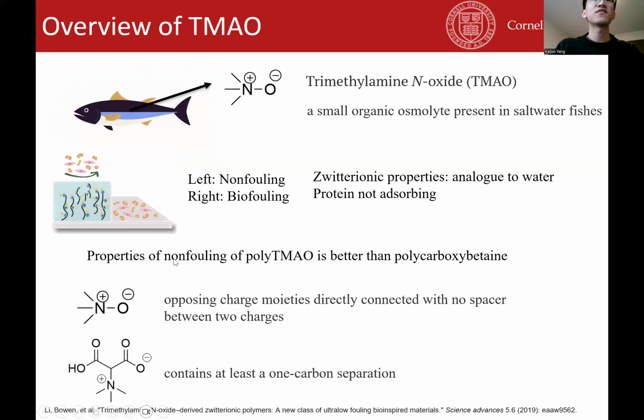Also, the non-fouling property of polyTMAO is better than polycarboxybetaine, which is also a zwitterionic material. From the structure, we can see the opposing charge moieties of TMAO are directly connected with no space between the two charges. However, the carboxybetaine contains at least one carbon separation. The longer the carbon separation chain, the more hydrophobic it is. So the non-fouling property will go down with the increasing carbon separation.